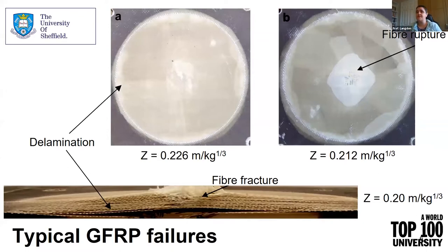So on the screen, I've shown you a typical glass fiber epoxy panel. You can see two images there from two different tests. You're looking at the rear side of a panel in those two squares at the top of the screen. The exposed area is the circular part with the white scoring around the edges. And what I hope you can see there is the brown corners are the original color of the glass fiber epoxy, and the whitened area on the inside of the loaded section has delaminated considerably. That's why it's whitened, in case you're wondering.